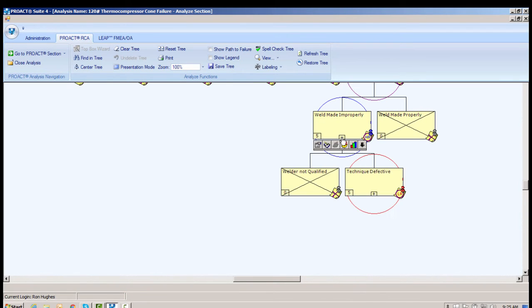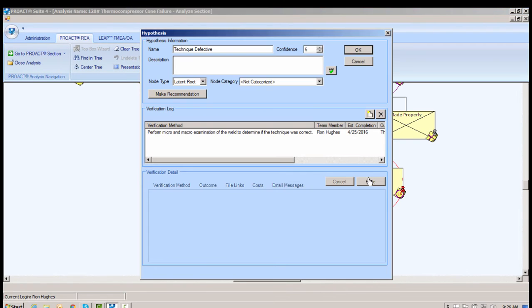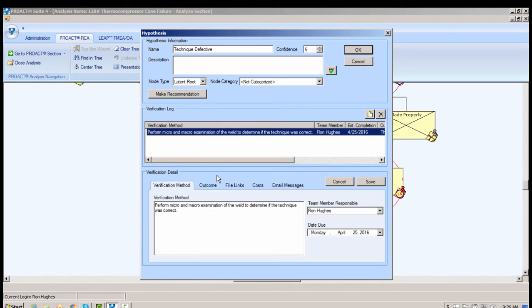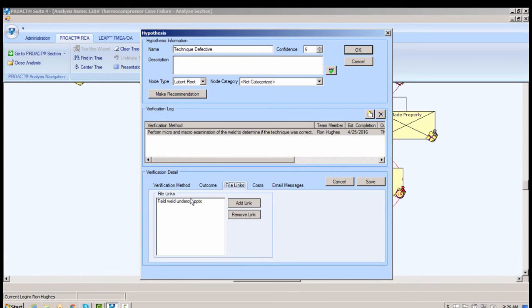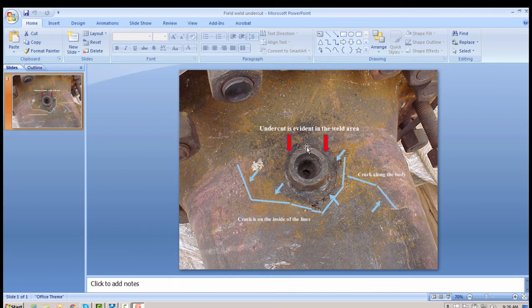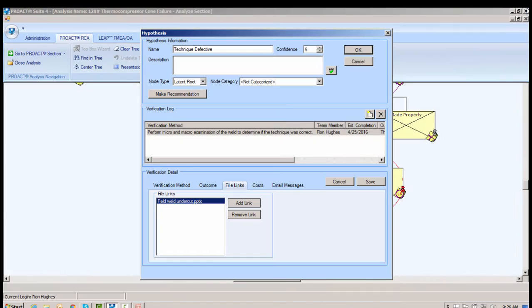Well, how can that be? Well, either the welder's not qualified or the technique is defective. We checked the welder's qualifications and certification. He is certified in accordance with ASME Section 9, so he's a certified welder. The technique is definitely defective, so we look at that examination again, and this is what we find. We can readily see the undercut, and we can readily see the cracking, and we can also see now and know for sure that it's been welding with too much heat.